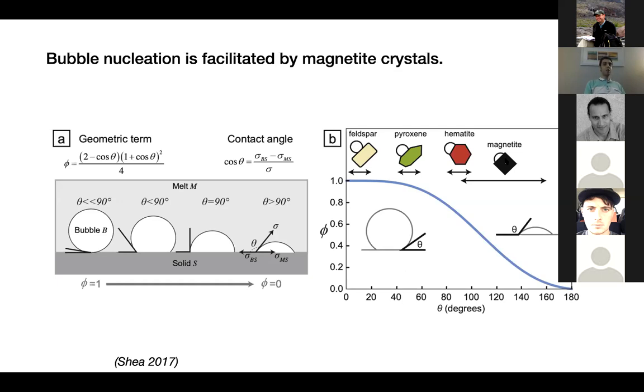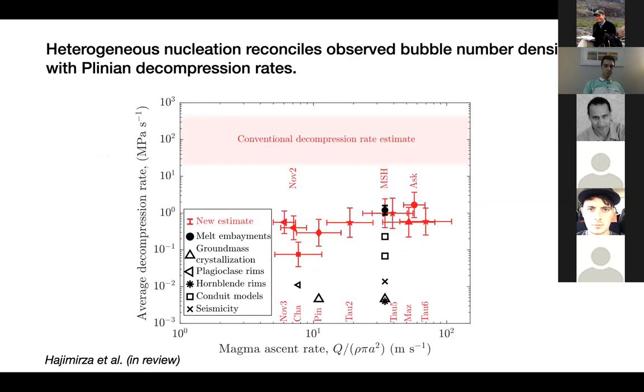Our model verifies that in order to reconcile the observed bubble number densities in all 7 eruptions with the pre-eruptive water concentrations, magnetite is the only mineral phase that can do that. From now on, we assume nucleation is heterogeneous on magnetite. By doing so, we simulated nucleation within each individual eruption. We estimated a decompression rate that allows our model to match observed bubble number densities. Estimated decompression rates on average are shown here with red symbols.